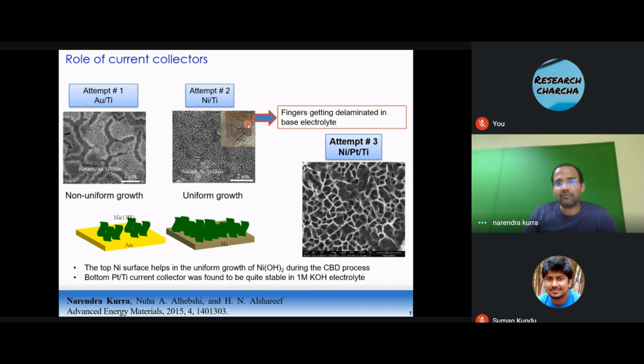However, when we started testing in the base electrolyte, potassium hydroxide electrolyte, we see the fingers getting peeled off. They completely started floating in the electrolyte. So this is where we came up with a tri-metal layer approach, where you have titanium as an additional layer in between, platinum as a robust material, which is robust enough against corrosive electrolytes and chemically compatible, and nickel as a top layer to ensure the homogeneous decoration of nickel hydroxide petals.